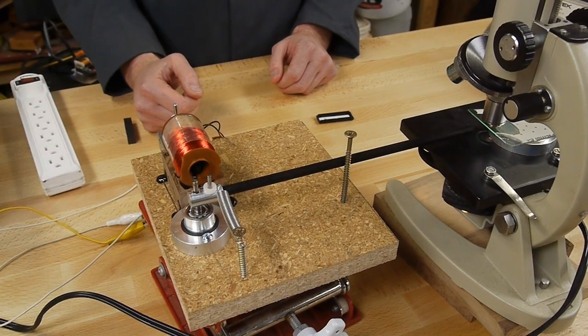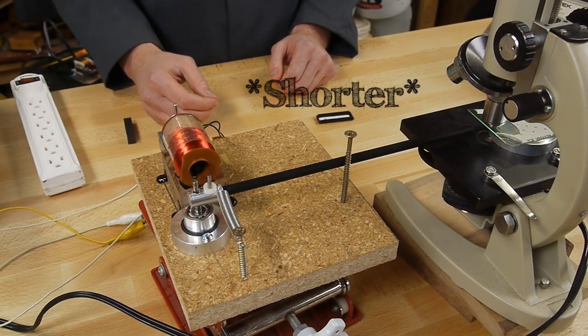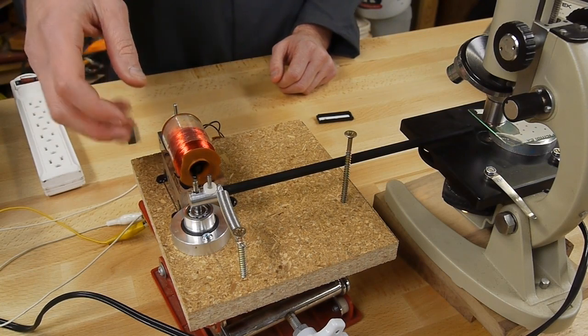I got video of that, and here you can see the wire moving. You can see it sort of click back and forth, and that is me pressing the button on and off. When the field is perpendicular through the ribbon face, the length is a little bit shorter. When I turn the solenoid on and the field is parallel to the ribbon, the length increases a little bit.